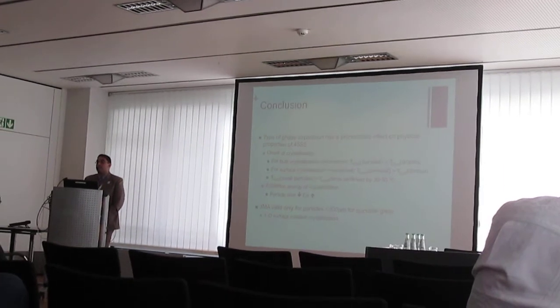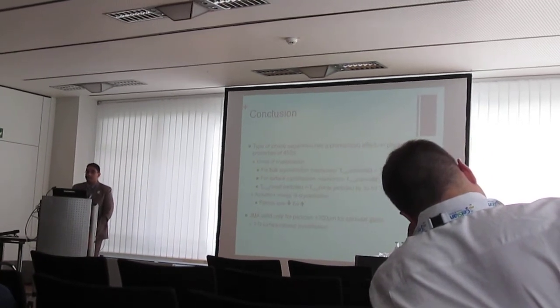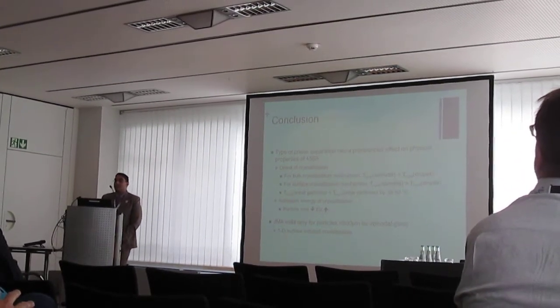Secondly, we determined that the activation energy of crystallization increases as the particle size of the Bioglass decreases, which I had a qualitative explanation for, but more work has to be done to determine quantitatively what exactly goes on in this situation. Finally, we determined that the JMA model is only valid for particles less than 300 microns in size for the spinodal phase separated glass, which led us to conclude that we have 1D surface initiated crystallization for this glass.